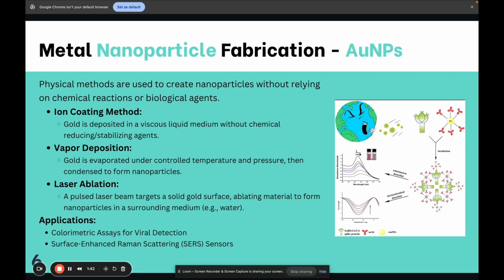this is very ideal for creating highly pure, uniform particles for sensor applications. Then comes the method of laser ablation, in which a pulsed laser beam targets a solid gold surface, ablating material to form nanoparticles in a surrounding medium. This actually produces very stable nanoparticles without the need for surfactant. There are other methods like mechanical milling and pyrolysis too.